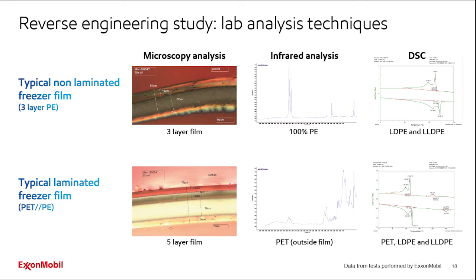For those two samples, we have used three techniques. The first technique is microscopy analysis. With that method, we can identify how many layers there are in the packaging structure, and we can also measure the thickness of each layer. Then, the second technique, infrared analysis. We pass a beam of infrared light through the freezer film, and then we get a spectrum, and that spectrum is a characteristic of the sample structure. With that method, we can really identify which type of polymer is used in the packaging structure. For instance, whether it's polyethylene or polypropylene or PET, right?